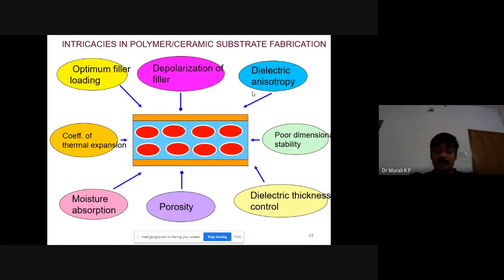Then dielectric anisotropy, which is very important, because if the dispersion of the ceramic in the polymer matrix is not uniform, then at each point the dielectric property variation, epsilon r and loss, will be varying. It will not be homogeneous. So that can create problems when you design a circuit on that, like fringing capacitance. A lot of such problems will come if you don't disperse the ceramic uniformly in the polymer matrix.